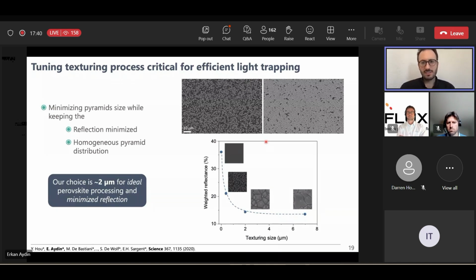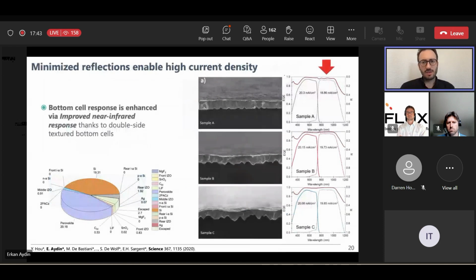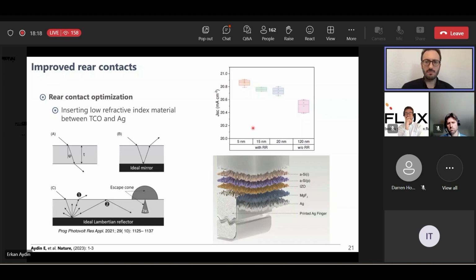If you use a spin coating method, the next challenge was making the perovskite a bit thick. So basically, we used more concentrated precursor solutions and optimized the process further. And indeed, this strategy worked. As you see on the right-hand side, we really minimized the reflections, especially in the near-infrared region. Well, for sure, if you deposit a conformal layer, you can get a similar effect, even better. But our method enabled solution-processed perovskites on textured interfaces.